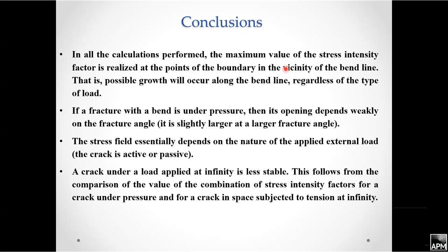Main conclusions. In the calculations performed, the maximum value of the stress intensity factor is realized at the point of the boundary in the vicinity of the bend line. That is, possible growth will occur along the bend line regardless of the type of load.